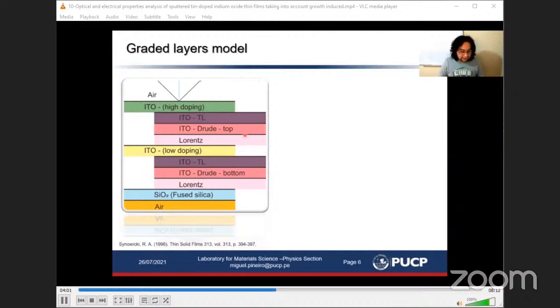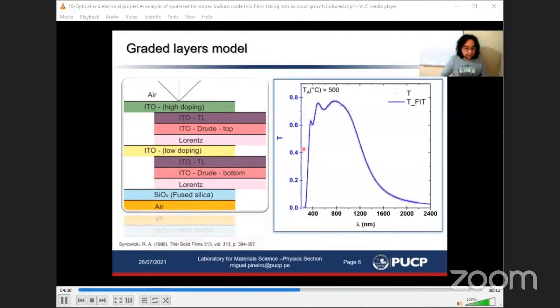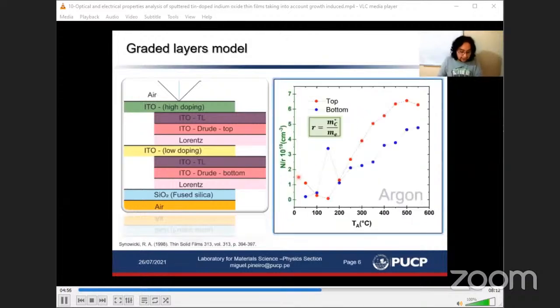Typically, the dielectric function modeling of ITO is performed by using the Drude model and Tauc-Lorentz model, considering only a single layer. But in this study, we model it as two layers. Both layers share the same Tauc-Lorentz parameters, but different Drude parameters in order to obtain different carrier density and mobility for each layer from the transmittance measurement. Now, we show the transmittance as a function of the wavelength, where the experimental data are small triangles and the solid line is the transmittance fit. The fit was obtained by using the previous model, the Drude model and Tauc-Lorentz model, and we found